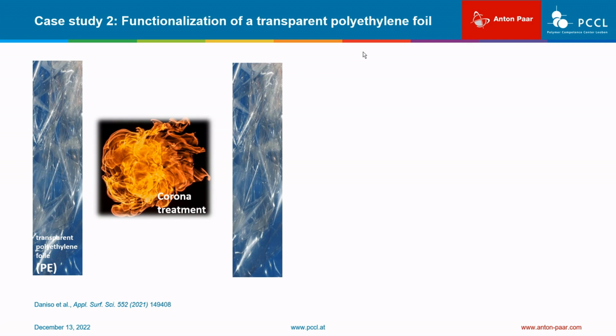Polyethylene films were first treated with a corona discharge. Corona discharge treatment is used to improve the bondability, wettability, and printability of polymers, particularly of polyolefin films. The reason for this improvement is the introduction of oxygen or nitrogen containing groups. The corona discharge leads to carbonyl, hydroxyl, and carboxyl groups.